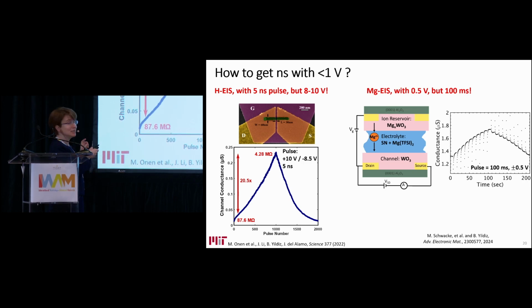But probably in the fine print, what you didn't notice is the very large voltages that we have to apply to accelerate the protons through these not-good-conducting electrolytes. So one has to go to an order of 8 to 10 volts at present to get to these speeds. We have similarly explored magnesium as the working ion. You can work with a small voltage, so 0.5 volt, but of course then you have to wait very long for the response, like tens to hundreds of milliseconds.